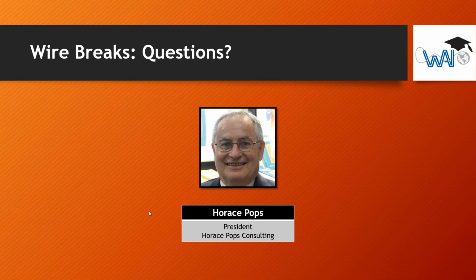Thank you. Next question. What is the source of crow's feet on the wire surface? Well, it can be a number of things. As I said, it's poor lubrication. So what happens is the wire being drawn doesn't have a lubricant between itself and the die. So therefore, the copper or whatever material you're drawing adheres or sticks to the die. Therefore, the material being drawn is rubbing against itself rather than the diamond or polycrystalline material. And therefore, you've got very, very high friction, and therefore you will get both fines being formed and possibly wire breaks taking place.